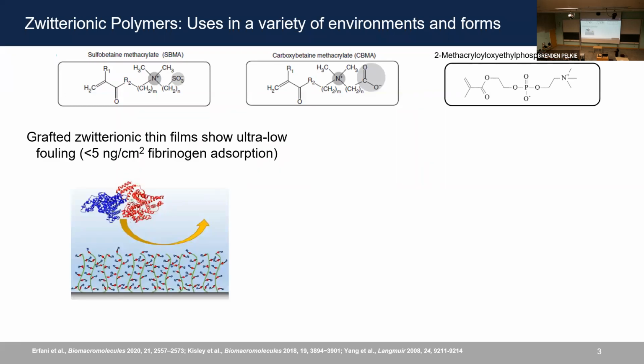We care about studying Zwitterionic polymers, especially to modify surfaces, because they show very low non-specific protein adsorption, otherwise known as fouling. They're even categorized as ultra-low fouling, which means that for blood contacting devices, it has been shown that modifying the surfaces with grafted Zwitterionic polymer leads to less than 5 nanogram per centimeter square fibrinogen adsorption, which is the gold standard for avoiding the body's immune response.